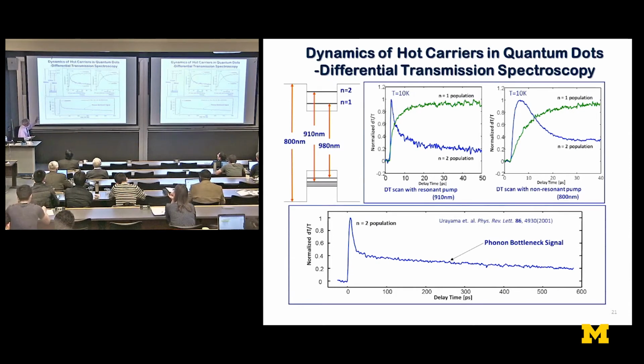But he observed that under certain conditions, the excited state population showed something like this. And this was a signal predicting a phonon bottleneck problem. Now, the N1 to N2 separation in these quantum dots can be larger than the optical phonon energy. And if that is the case, then, of course, the carriers just can't come down unless there is some other mechanism.